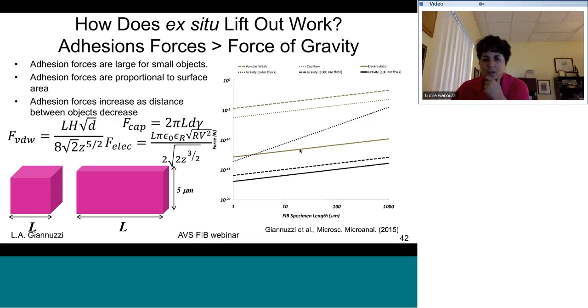So if you look at this, this predicts that you can actually manipulate samples on the order of a millimeter or longer. It's interesting, if you take a look at the van der Waals force equation, there's two things that we know. One, of course, is that the adhesion force is proportional to the surface area, so the more surface area you have available, the greater the van der Waals force is. And also, this Hamaker constant, H here, is a material constant, and this varies 2 orders of magnitude over the periodic table. So if you take a look at this log-log plot and vary at 2 orders of magnitude, you've still got 10, 12, or more orders of magnitude larger than the force of gravity acting on these small samples. So this is why it works, and this is why it works very well and reproducible.